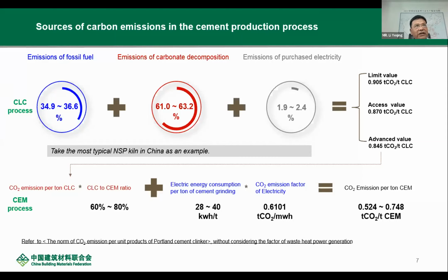As to emission source, the carbonate decomposition accounts for 61 to 63%. This is about 525 to 545 kilograms per ton clinker. Emissions from this aspect depend on the clinker composition, whether the alite C3S is higher or lower.